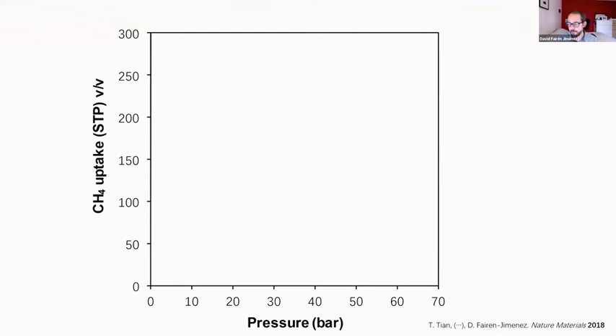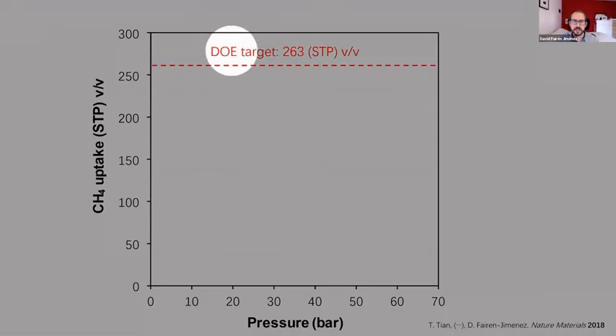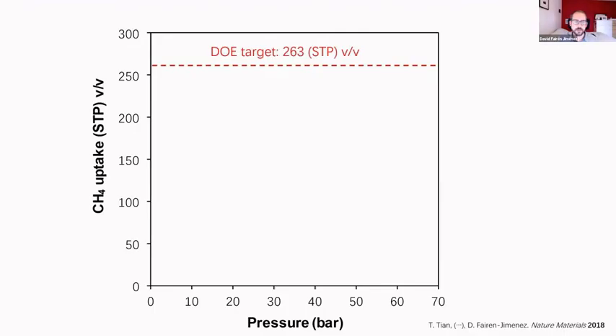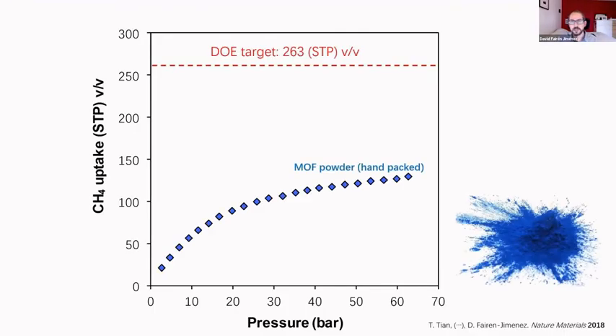We are obviously focusing these days on hydrogen, okay? But natural gas storage was really good because there was a Department of Energy target. People said that with MOFs, in theory, we can reach these values, but experimentally nobody was able to reach them, okay? That was the best experimental result that we found for a porous material, including activated carbons and metal organic frameworks. This is for a MOF called HKUST-1, okay?